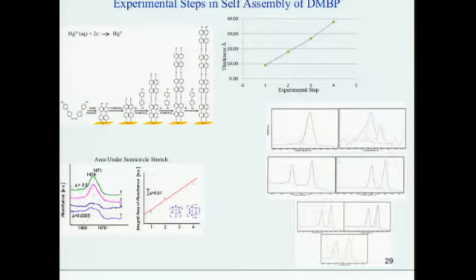The XPS results, again, show what's unique about mercury. Again, we get the multilayer, but we see 2 different mercury species. We see mercury 0 on the first and second layers, but then after the 3rd and 4th layers, we see actually mercury 2 oxidation. I'm still interested in figuring out what that's about. I'm still fascinated by that finding.